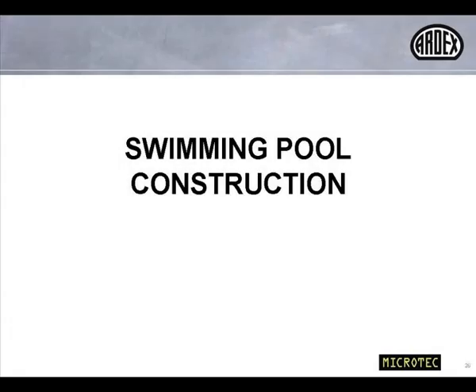Swimming pools must be designed and constructed to meet water tightness criteria in accordance with British Standard 8007, 1987. Which states that during the 7-day test period, the total permissible drop in water level, after allowing for evaporation, should not exceed 1/500th of the average water depth of the full tank, 10 mil or another specified amount, such as the SPATA standard of 12 mil. Note that ceramic tiling is in addition to, rather than a part of the tanking system.